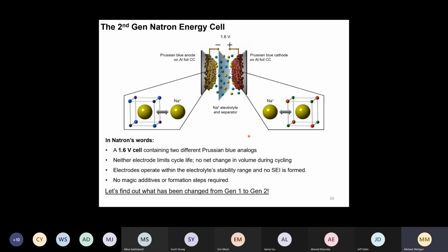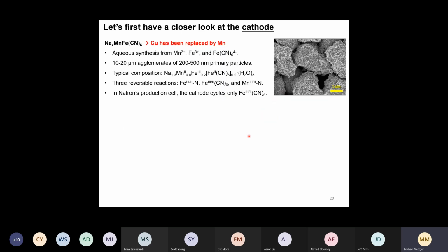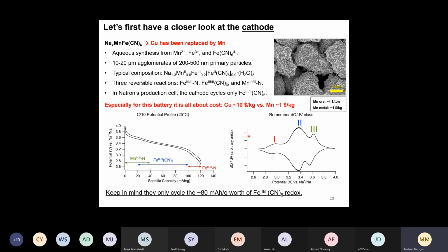Okay, so just very quickly. The Natron energy cell we discussed, 1.6 volts in their second generation cell, 2 Prussian blue analogs on anode and cathode. And we already looked at the cathode. We noticed that they replaced copper by manganese. And of course, Jeff is right. This incredibly cheap value of $4 per ton would be for manganese, or the manganese metal is more on the order of maybe $1 per kilogram, roughly speaking. So it's still cheaper than copper. And that's, I believe, why they replaced this.